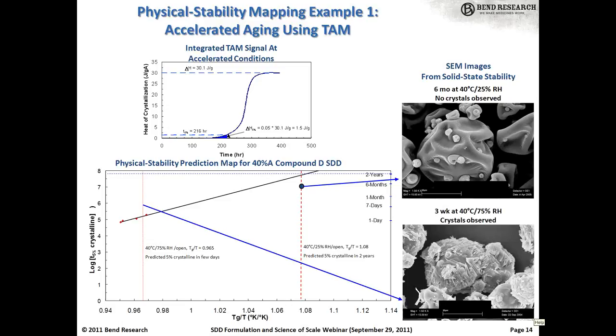more rigorous physical stability mapping using a technique like isothermal calorimetry, or TAM, in which you actually measure the kinetics of crystallization at a given condition. So in this instrument, what you're doing is setting up a sample at a controlled temperature and humidity for many days to weeks, and measuring heat flow, and so you can actually observe the time it takes to reach crystallinity. We typically define it as the time to reach 5% crystallinity as a good metric, although that's admittedly somewhat arbitrary.